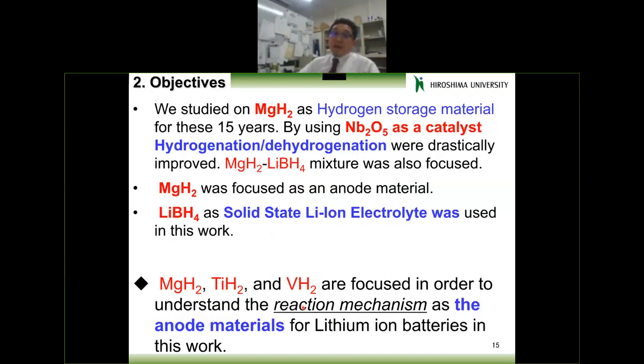But anyway, we have studied magnesium hydride as a hydrogen storage material for these 15 years. By using niobium oxide as a catalyst, hydrogenation and dehydrogenation were drastically improved. And also we focus on the magnesium hydride and lithium borohydride mixture or composite. That is our target material. And as I already introduced, magnesium hydride for the anode and lithium borohydride as the solid electrolyte. So we are interested in these materials.